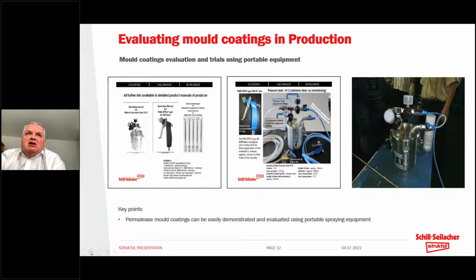So in terms of the practical application of these coatings, as mentioned, they need to be sprayed onto hot, clean molds. The coating is designed to adhere to the mold, to the substrate, and of course then we need specific spray equipment to achieve that. It's not as complicated as it sounds. We would recommend an air spray gun with a relatively fine nozzle. These are some technical drawings and information that we developed together with a leading supplier of such equipment based in Germany, but we're aware of equivalent equipment available globally.